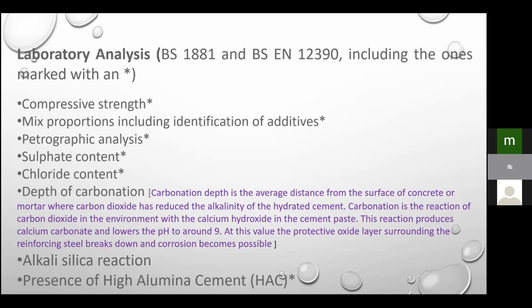So the carbonation depth is the average distance from the surface of concrete or mortar where carbon dioxide has reduced the alkalinity of the hydrated cement. When the carbon dioxide penetrates, that reduces the alkalinity of hydrated cement. As you know, hydrated cement is basically alkaline, with a pH of maybe 12 to 14.